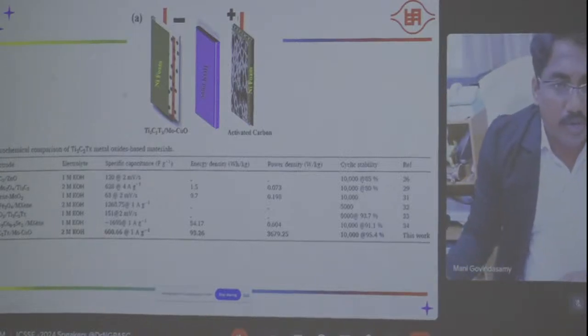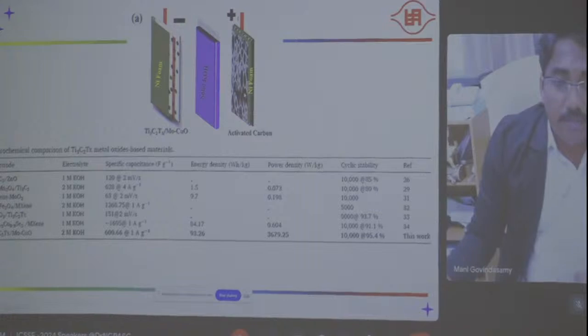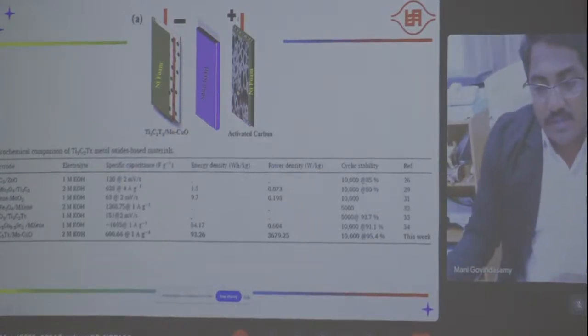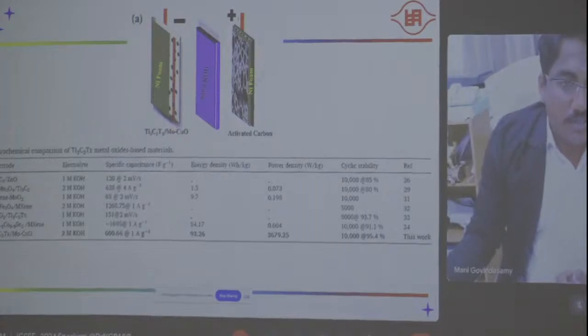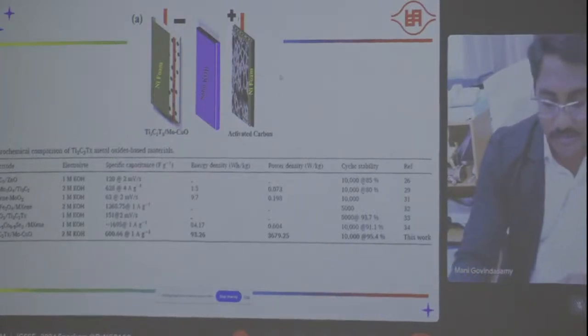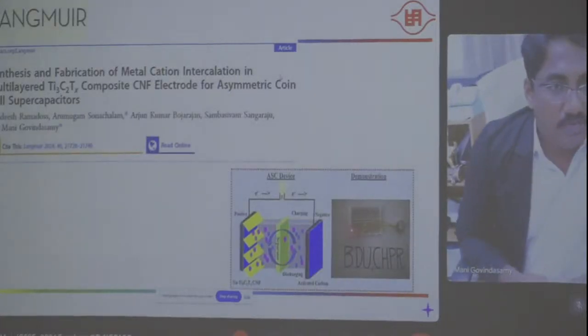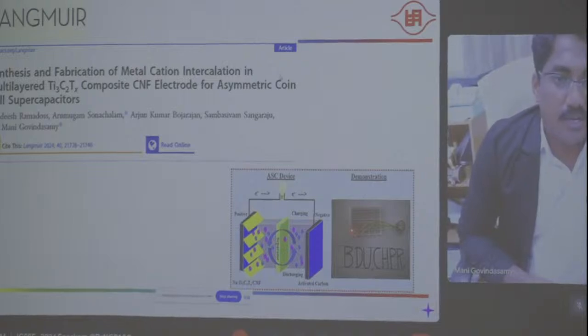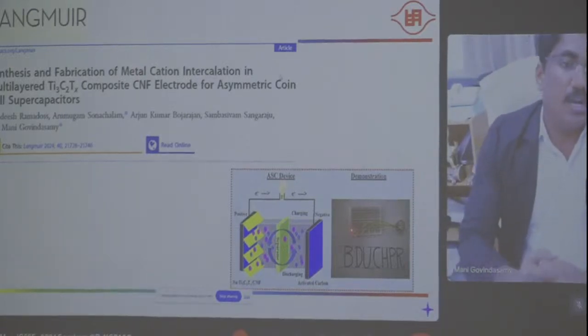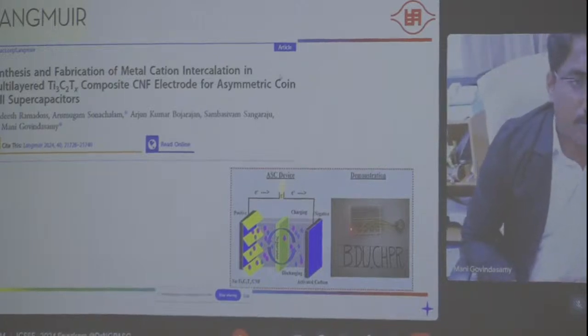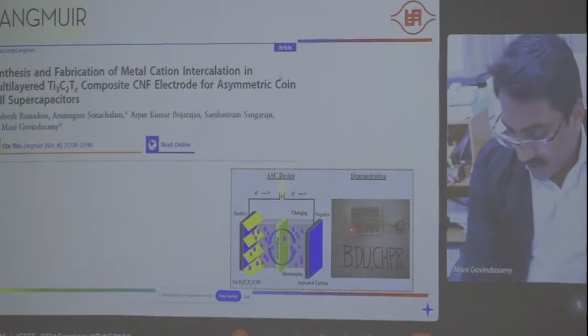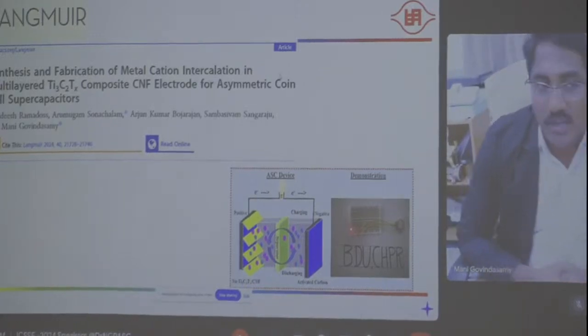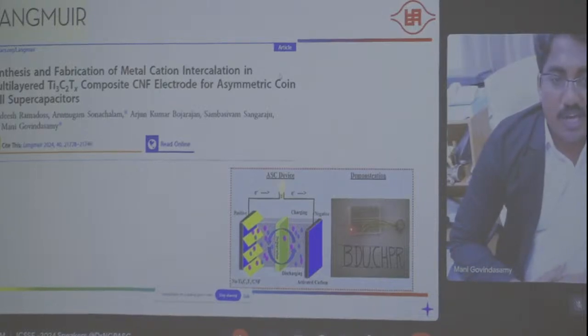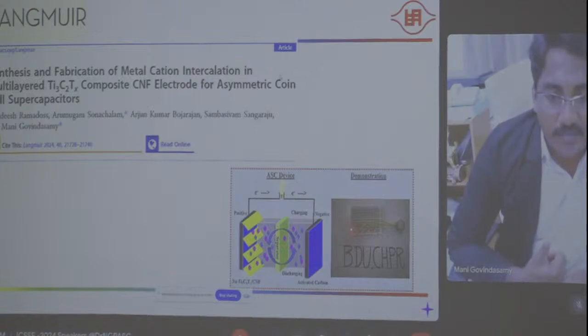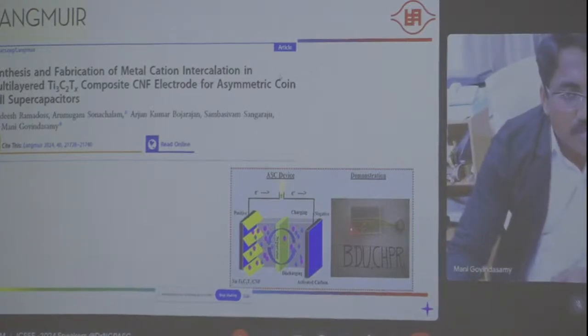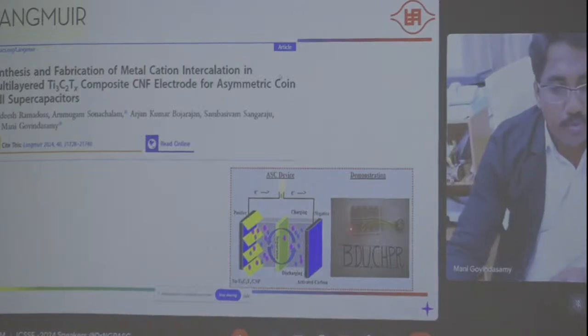For example, one electrode we develop as supercapacitor material, and the other electrode as battery material. That means we are working on the supercapattery. When we go for the battery concept, we need to develop high energy density. That's why we are developing supercapatteries as energy storage devices. In this work, we develop metal cation intercalation using the multi-layered MXene composite. For example, we can combine with carbon. Even though we can use titanium carbide, when we additionally use carbon related materials, particularly carbon nanofibers, we can enhance higher power density. That's why we develop carbon related composites for asymmetric coin cell supercapacitors.